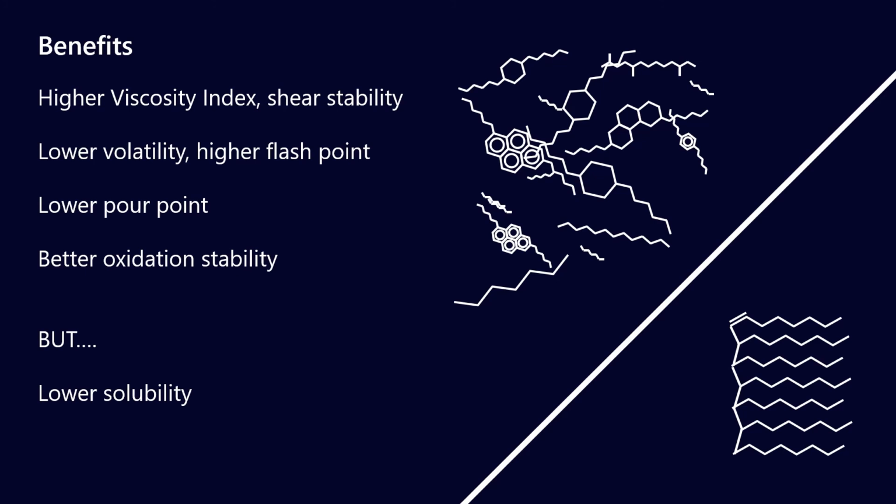With the mineral oils, particularly with group 1s, the fact that there are some polar molecules within the bulk oil means that there is some solubility to it. PAOs are very non-polar, and that can be a challenge for formulators because most additives don't mix in very well with a PAO, and so often you'll need a co-base stock like an ester included in the formulation to actually hold those additives in solution.